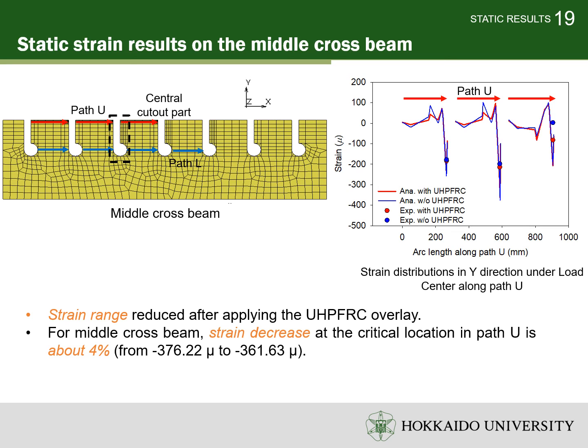From the strain distribution along path U and L, it can be seen that the strain level as well as the strain range in the model with UHPFRC are smaller than those from the model without the strengthening layer. This demonstrates the increase in overall stiffness of the steel bridge deck reinforced by the UHPFRC. For the middle cross beam, the strain decrease at a critical location in path U is about 4%.